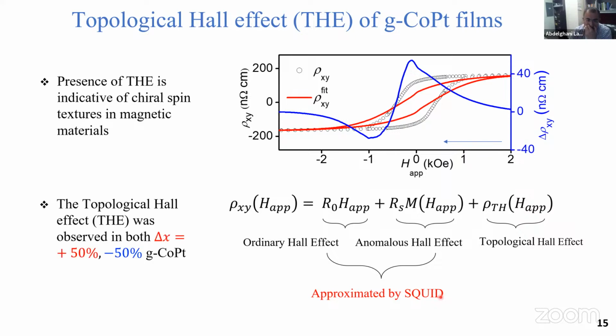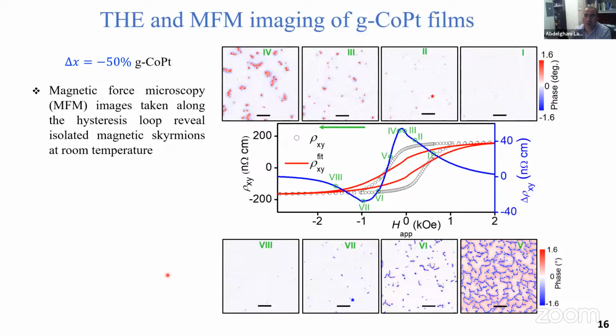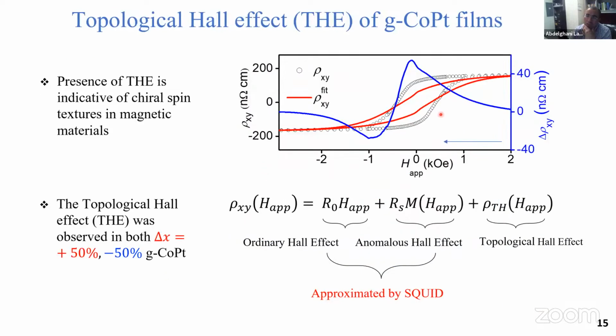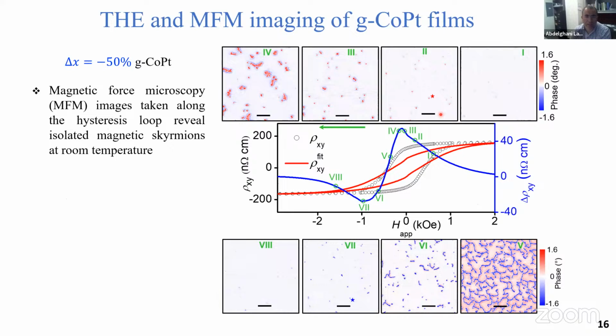And then, we also did some measurement on the positive sample. I will show you later. To check whether, because usually this topological Hall effect is indicative of the presence of spin textures, we used magnetic force microscopy here at UNL.